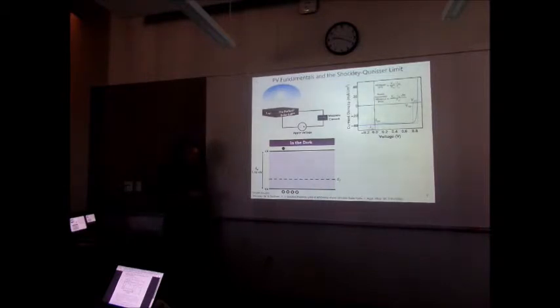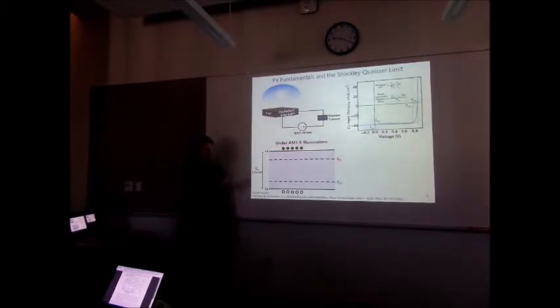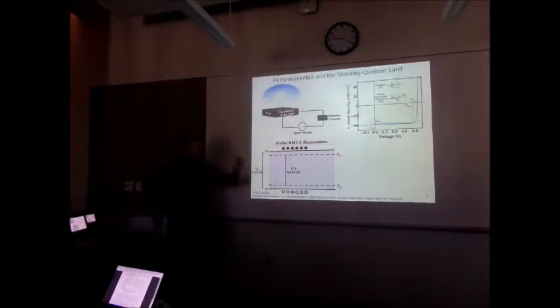So what does this mean from a solid state physics perspective? If I imagine a semiconductor with a valence band and conduction band with unallowed states here, we can define a Fermi level, which is the chemical potential for electrons in the conduction band, holes in the valence band, and when we illuminate it, you get splitting of the quasi-Fermi levels. And this splitting of the quasi-Fermi levels is directly related to the open circuit voltage in a device. So this is a direct connection between the material, and I'll talk about why this is important towards connecting it to the VOC here in a second.